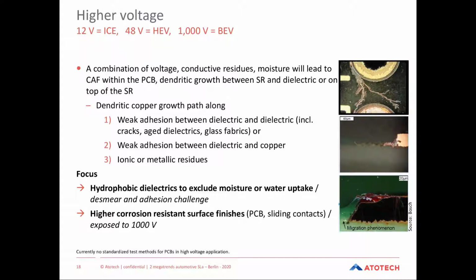With higher voltage, another focus area will be the surface finish. With higher voltage and thus with a wider potential range between conductors, corrosion resistance of surface finishes will get more important. As an example, taking silver as a surface finish, moisture and high voltage will create strong dendritic growth. Surface finishes enabling high corrosion resistance, such as high phosphorus ENIG or immersion tin, are both promising candidates to survive with moisture and ionic contamination in this kind of environment. If wire bonding is required, then electroless palladium, autocatalytic gold, or nickel palladium gold are good choices also to survive.